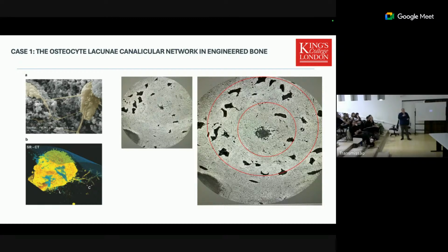So what we've started to understand is that unless you reform this osteocyte network within a graft, the body is no longer in control of its mineral density in how it would normally do it in health. And this is why I believe that the rate of bone loss in peri-implantitis is very different to the rate of bone loss in a non-grafted site.